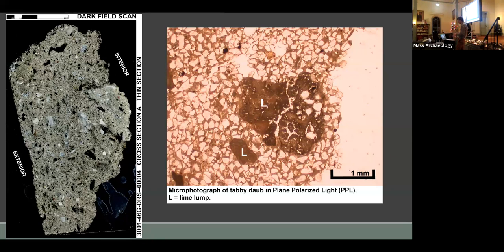So when water is added to quicklime, an action referred to as slaking, a chemical reaction occurs, producing heat and steam. Depending on the amount of water, quicklime is either transformed into a powdered form or into a lime putty, both of which are calcium hydroxide. How exactly slaking was accomplished in Tabby making is not known and likely varied depending on the workforce and project demands. Lime putty was traditionally left to cure in pits or barrels for weeks, months, or years at a time before being mixed with aggregate and used in construction.